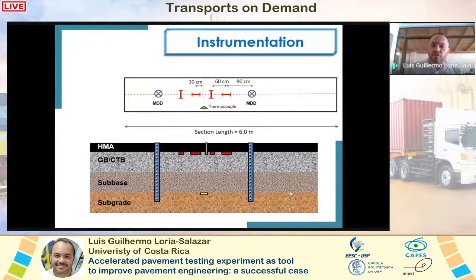We have the instrumentation. The red ones you can see are the typical I-shaped LVDTs. We have the multi-depth deflectometers, the MDDs. We have thermocouples. The yellow one that you can see at the bottom of the subbase and on top of the subgrade is a pressure cell to measure the stresses at the subgrade level. The blue ones are the MDDs, as I mentioned. After that, we also put saturation indicators to know the saturation of the subgrade, the subbase, the granular material, or the cemented base.